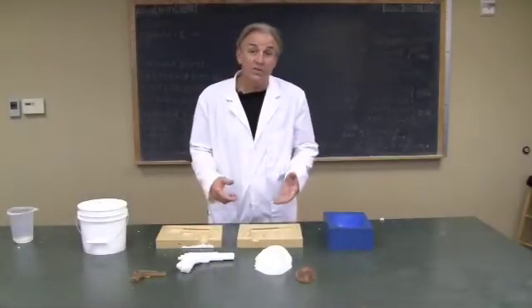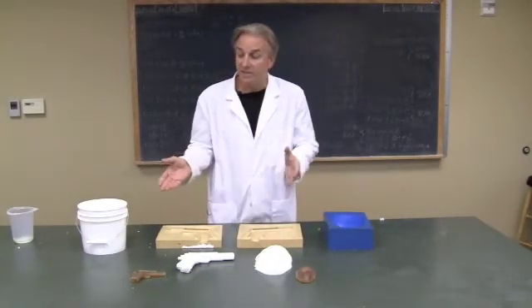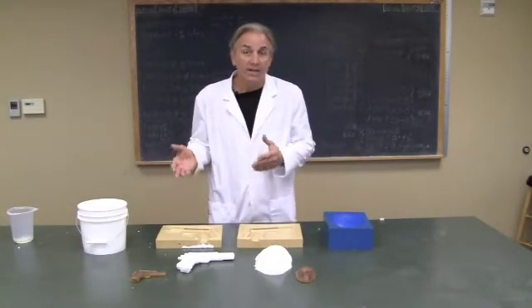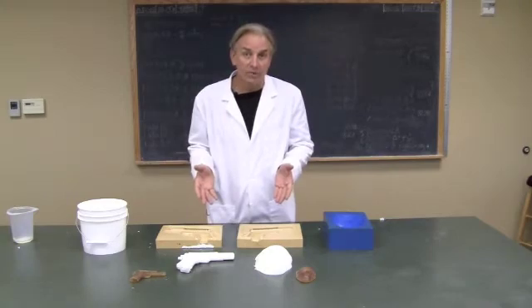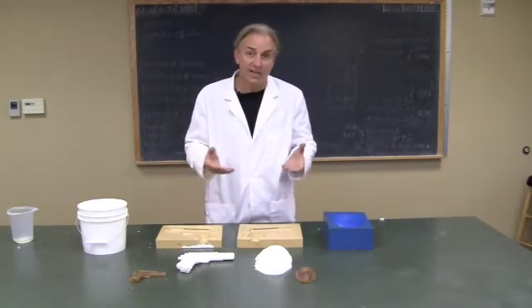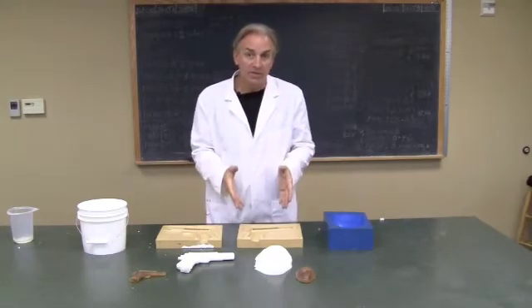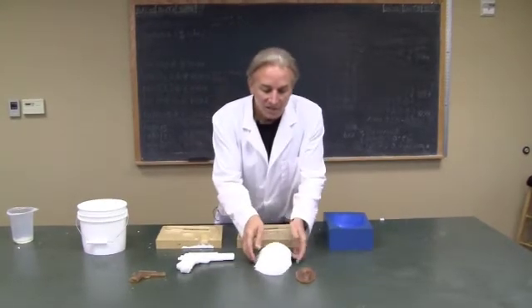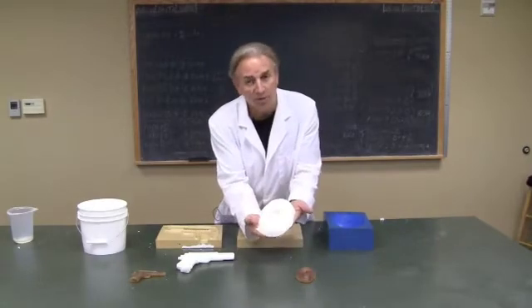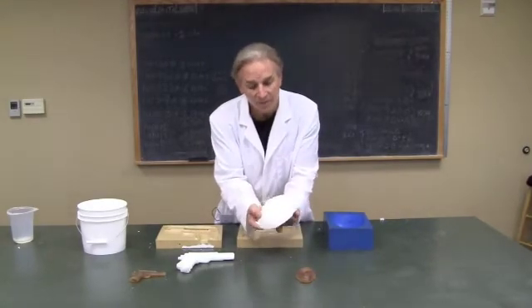We molded the parts, and you saw how fast they set up. In that case, I used 60-degree water. If you want to get slower curing rates, you want to use ice water with actually ice cubes in it. 40-degree water would probably double the working life of the material. As you can see, HydroSpan 400, when combined even with four parts water, has made a substantial polymer. It's not wet.